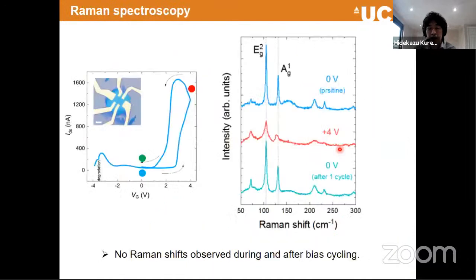Sorry, I didn't mention that. So first of all, this is Raman spectroscopy, and we measure Raman while we are gating. So I can just walk you through. This is the pristine state, the zero doping regime. This is the original vibration peak. When you dope it to about 3-4 volts, we can still maintain the peak position pretty well. There is a subtle line broadening due to the carrier doping, but we believe that the structure itself is maintained as before. Then we make a cycle in this regime and it simply comes back to the original state. So by looking at that, we think that there is no structural change while gating, for the electric doping one.